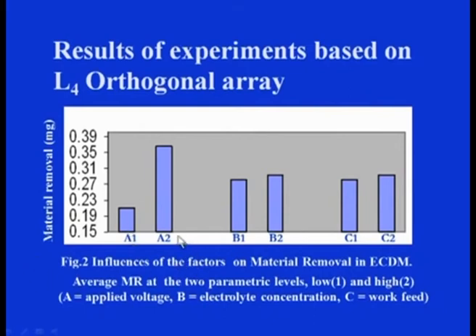And here, as we can see, this is the effect of applied voltage and this is the effect of the electrolyte concentration. Not much variation as far as the electrolyte variation is concerned, not much variation in the corresponding material removal, and so is the case with work feed rate. With the variation in the work feed, there is not much change in the material removal, however, little changes are there. But as far as the applied voltage is concerned, there is a huge difference between two levels of voltages applied on the material removed. These results were produced in IIT Roorkee.